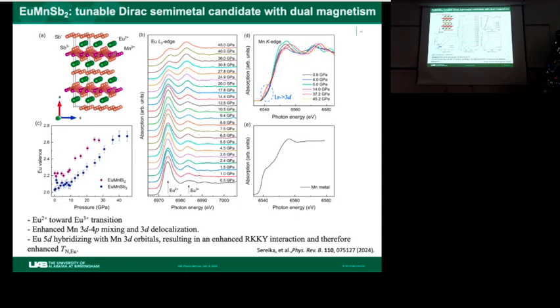And we also found through X-ray absorption at the europium L3 edge and the manganese K edge that there is significant hybridization of europium 5d electrons with the manganese 3d orbitals, and that could be the reason for the enhanced magnetic ordering temperature.